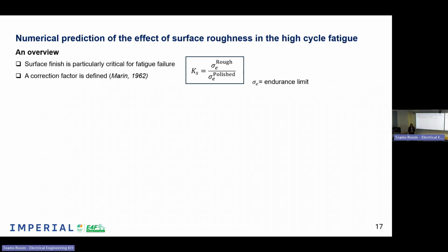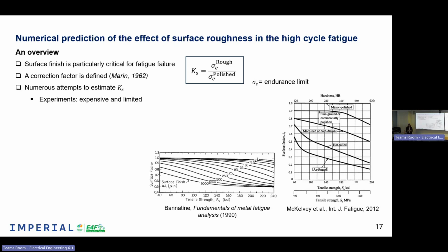So surface finish was always very well known to be affecting fatigue. And in the 60s, Marin introduced a correction factor, a coefficient that was measuring the effect of the surface roughness in fatigue. This coefficient is just the quotient between the endurance limit, the parameter I've mentioned to you in the previous slide, of the rough specimen divided by the endurance limit of the polished specimen. So there were many attempts in the literature to measure this KS, this surface factor.